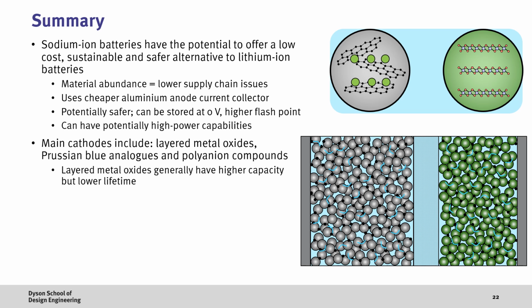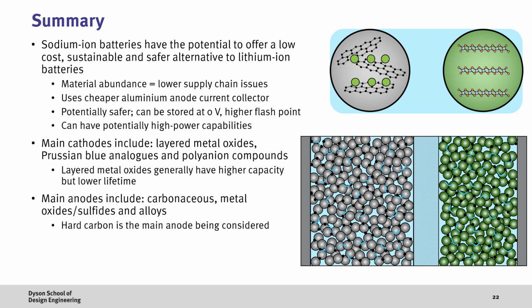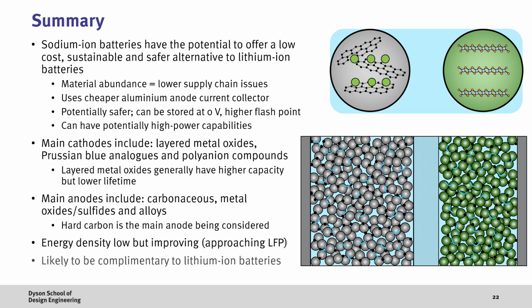Here, the main cathode materials are layered metal oxides, Prussian blue analogues, and polyanion compounds, with layered metal oxides generally having the highest specific capacity, though Prussian blue analogues have potentially good cycling stability and polyanion compounds good thermal stability. The main anode materials include carbonaceous, metal oxide, and sulfides, as well as alloys, with hard carbon being the most likely to be commercialized first due to its reasonable specific capacity and good lifetime. However, it's important to note that energy density is still low compared to lithium-ion, but it is improving. Finally, I think that sodium-ion batteries are unlikely to completely displace lithium-ion batteries, but rather they will be complementary to them as overall demand for batteries increase.